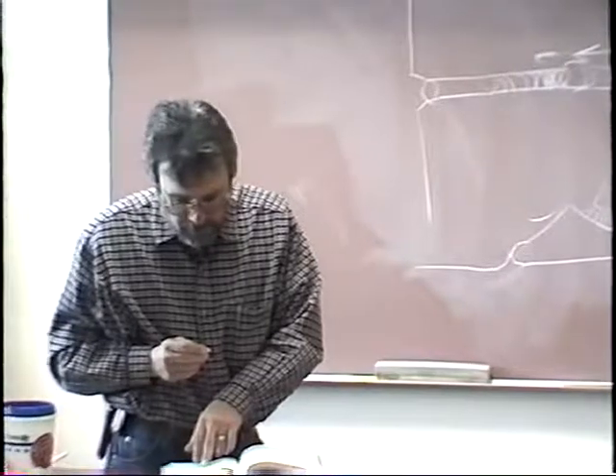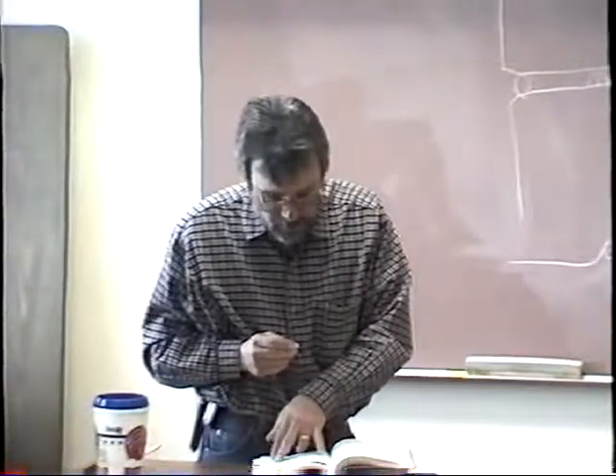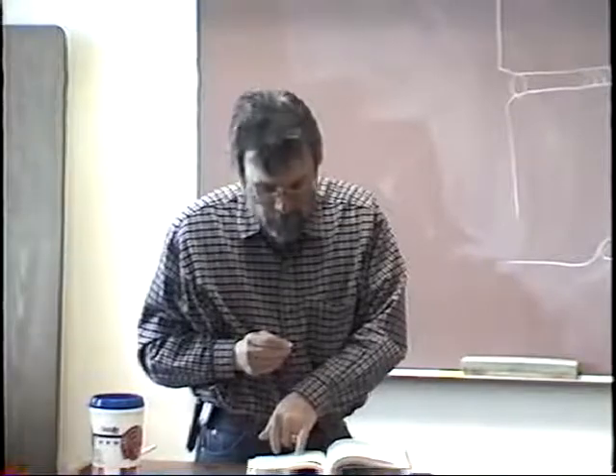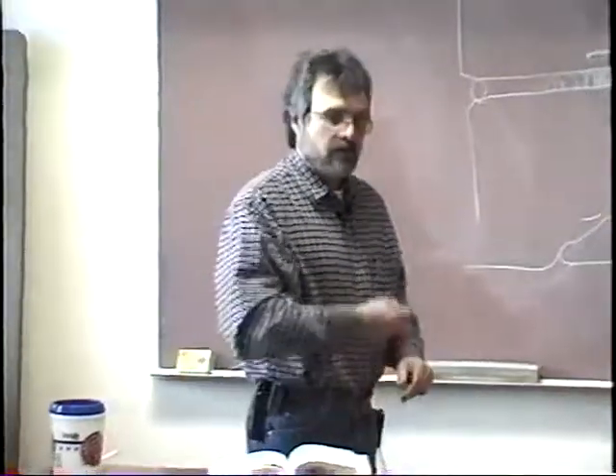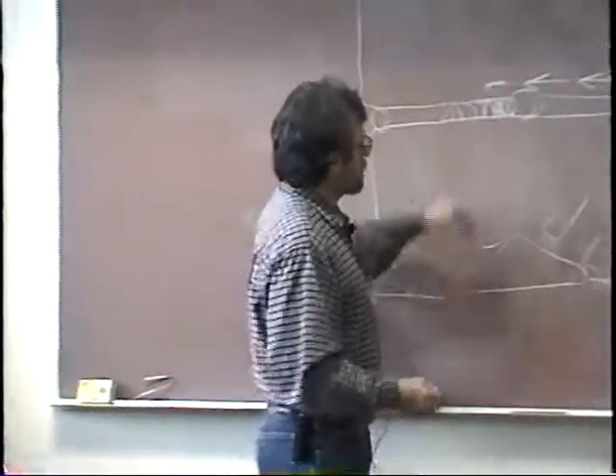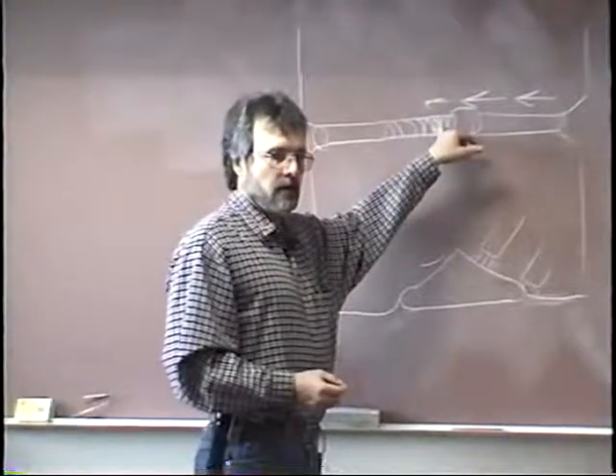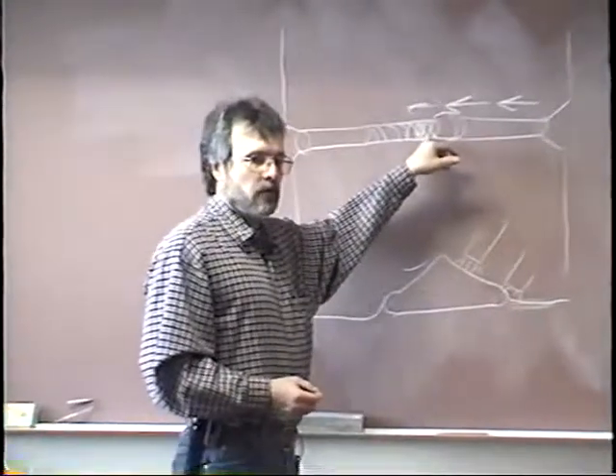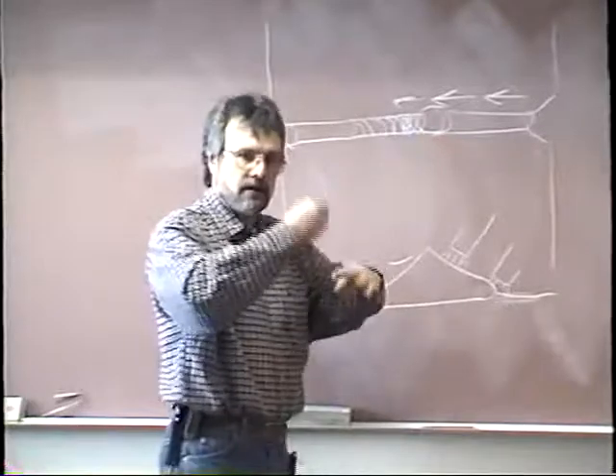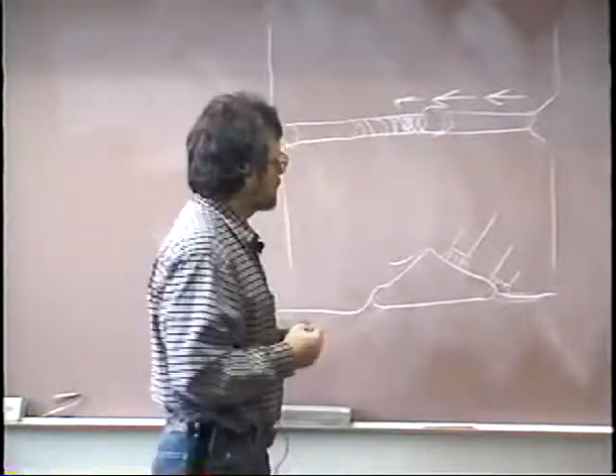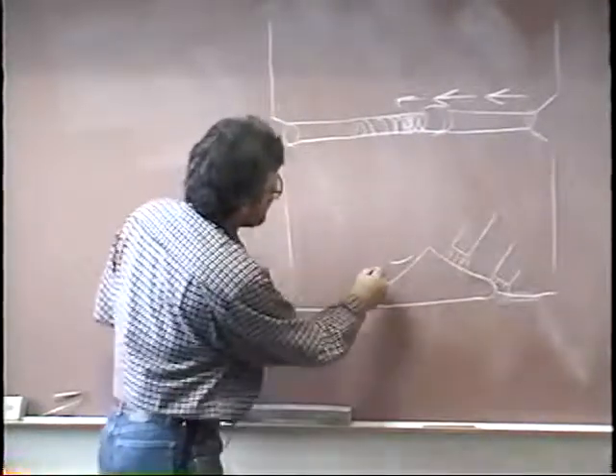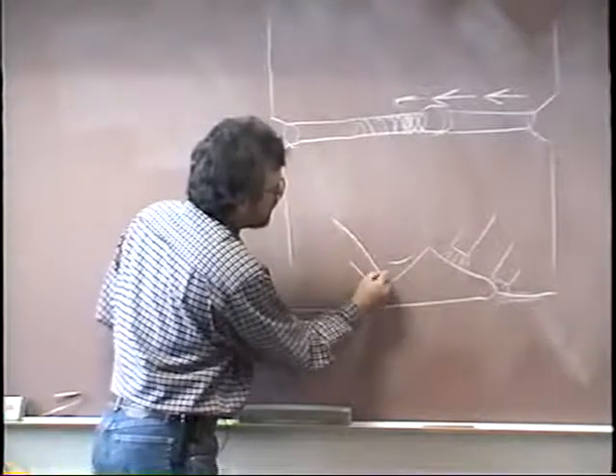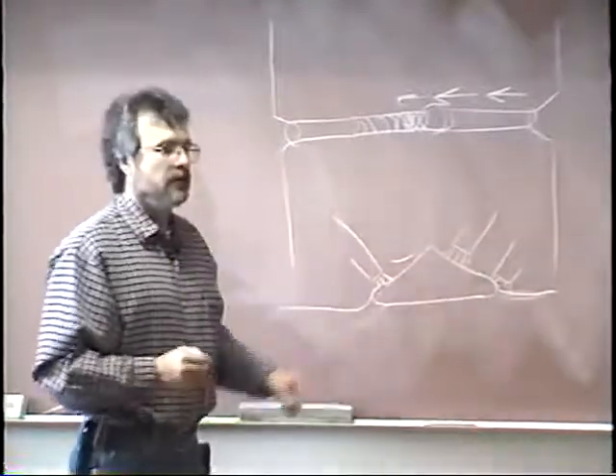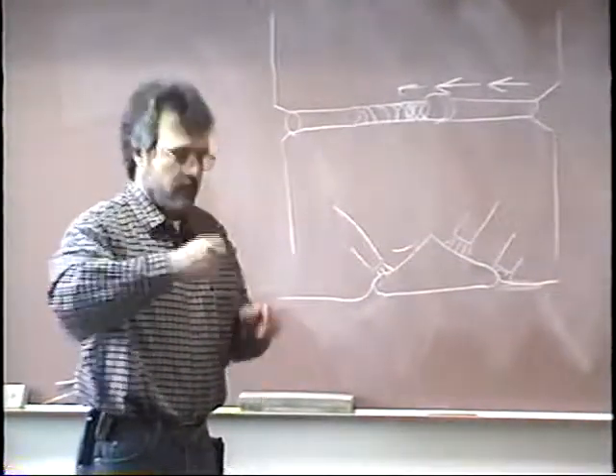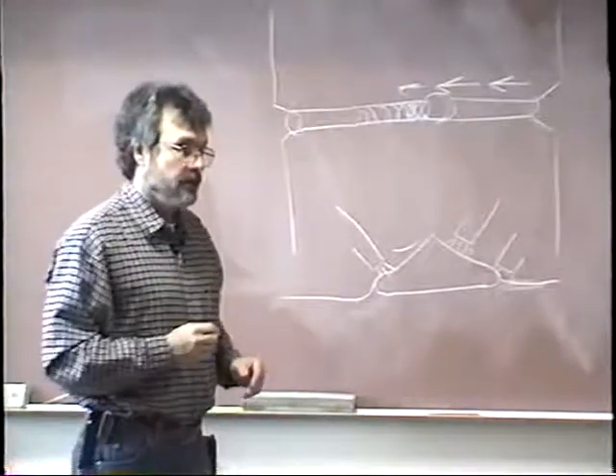It may even be advisable to pause momentarily a few times when the arc is over the heavy end of the bead. So again, it's just like when we were coming out of that and we heated the end of a weld about 1/4 of an inch back and the hot knife through butter technique. Same thing here. He's actually saying that you may even want to pause over the end of that tack a little bit as you're whipping to preheat it enough to get that good tie-in.